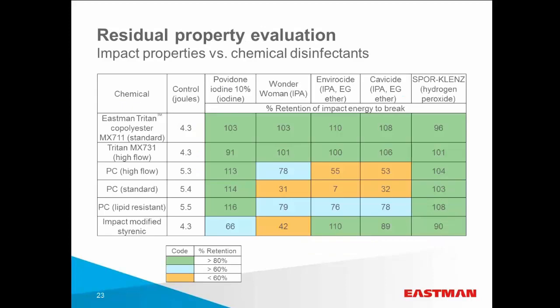So here's some data showing the Eastman Tritan copolyesters. There's a standard flow, MX711, our standard grade. We have the high flow grade, MX731. The chemical compatibility or chemical resistance of those two materials against some of these common disinfectants is holding up very well. You look at high flow polycarbonate, standard flow polycarbonate, or even the lipid resistant polycarbonate, you're seeing chemical attack based on some of the active ingredients in these disinfectants. The other one is the impact modified styrene in the lower part, and it also shows chemical attack, mostly from isopropyl alcohol and iodine. Next slide, please.